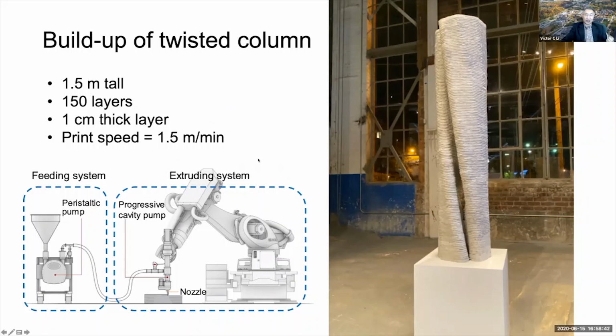These are just some highlights of research on ECC as a 3D printable ink. In the last year, we were able to print a twisted column about 1.5 meters tall with 150 layers, each 1 centimeter thick, and the print speed is 1.5 meters per minute. We use a 6 degree of freedom robotic arm system combined with a progressive cavity pump at the nozzle, which takes the material from the hose, which is pumped through using a peristaltic pump connected to the mixer where the material is fed in.